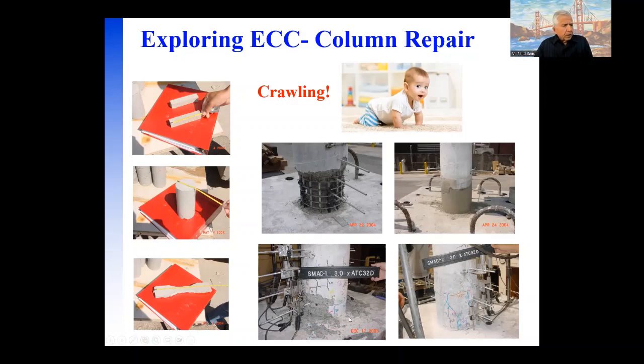The picture on the left shows the one with conventional concrete at an intensity of earthquake, let's just call it 3 times ATC. Then when we retested that column after the repair with ECC, the damage is what we saw in the bottom right side. So you notice in this one, we have some surface cracks, but nothing like what we have on the other one. So if you go to a bridge site and you see this condition, you say, well, actually, we don't need to close this bridge to traffic. So it became very attractive.